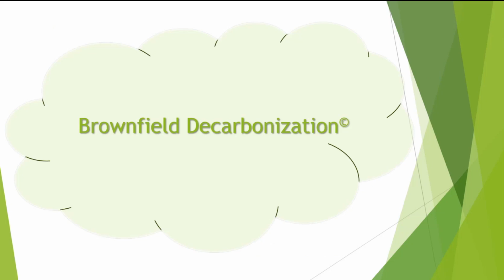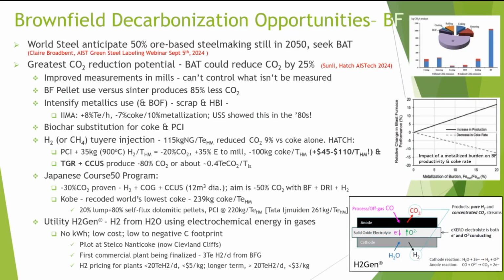So if we look at the opportunities on the brownfield decarbonization site, blast furnaces obviously would be the prime objective. We're still looking at 50% of the world's iron coming from blast furnaces in 2050. So we need to do something about those that remain. It is the greatest potential for CO2 reduction. Improving measurements in the mill would be the start. Blast furnace pellets, we already know, reduce the CO2 by 85% compared to sinter.